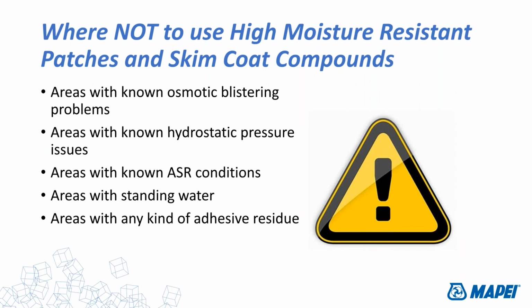I can help out a little bit with that as well. What's causing this problem? We don't want to deal with osmotic blistering. We don't want to deal with hydrostatic pressure issues where the water is literally oozing up from underneath the floor. Areas with known alkali silica reaction, not a very common problem in the flooring industry, but more in exterior concrete applications, but it's something we need to be aware of.